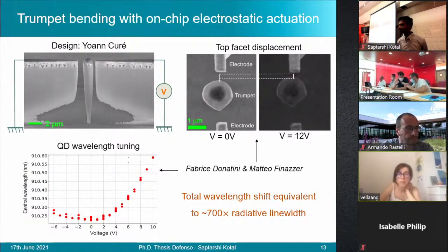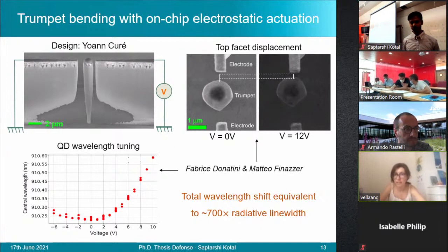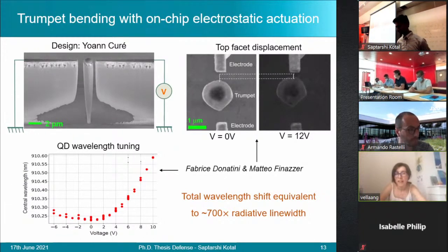Okay, I have one other question about the displacement of the trumpet you observe by SEM images, as you show here, and this displacement was really important, more than 100 nanometers. So you said it doesn't match with the simulations. But if we look at the tuning of the wavelength, and we calculate from this shift the displacement expected from the trumpet, the value I calculate is a few nanometers. So in this case, you are not so far from the value you calculate by your simulations.